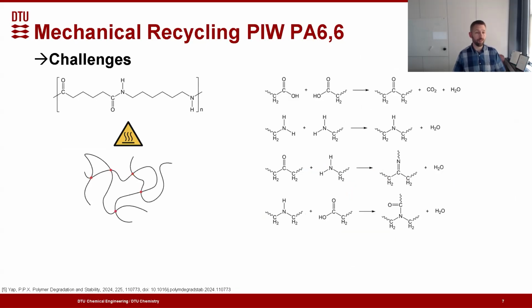However, once we have made these functional groups, we can also expect them to start reacting, and therefore we also, in these systems, expect the opposite reaction to take place, namely cross-linking, where we start to form networks or at least branch structures in this system as heat and temperature, as well as processing and shear due to the processing, is being applied to the polymer melt.